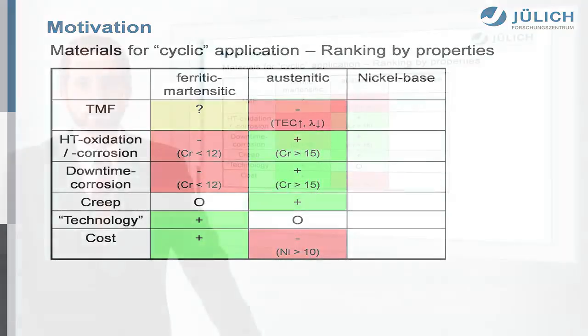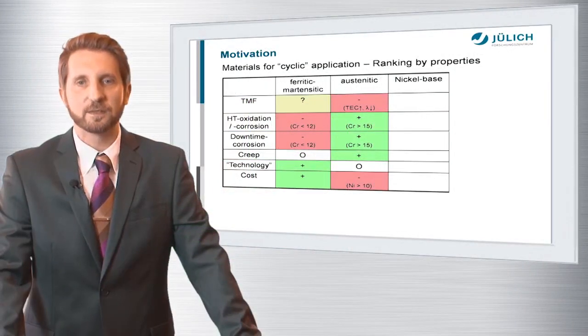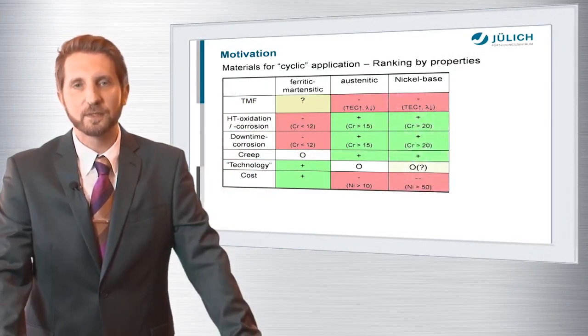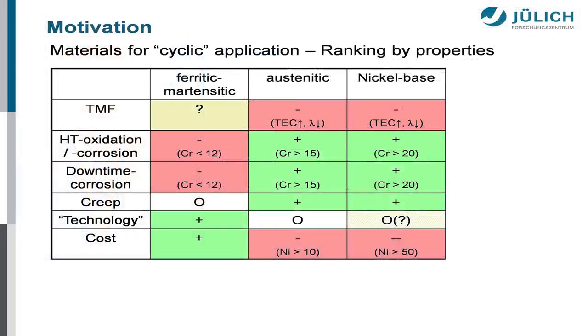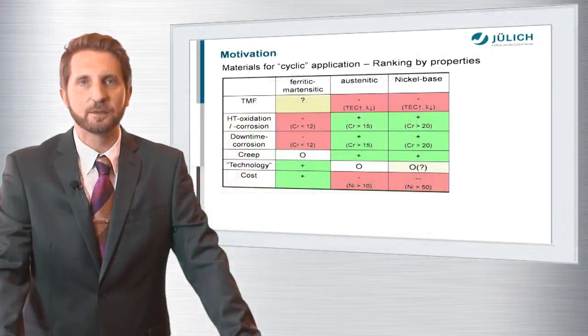If we now look into alternative materials like the austenitic and the nickel-based alloys, the picture is a little bit reversed, a little bit different. Typically, their thermomechanical fatigue resistance is considered to be worse because their thermal expansion coefficients are much higher and their heat conductivities are lower. Oxidation, corrosion issues, downtime corrosion issues should not be a problem because most of these grades feature chromium contents higher than 15% or even 20% in case of the nickel-based alloys. Creep resistance is not a problem too because these materials are stronger. Technological issues are, let's say, more or less solved because a lot of money has been invested, especially in the nickel-based field during the last 10 to 15 years.